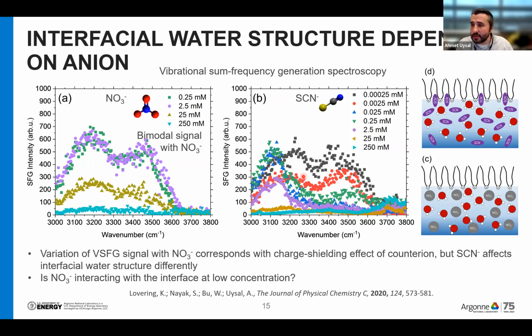And one more note about this data, I really love this data, because when you look at this, we are increasing the bulk concentration of nitrate 10 times from 0.25 to 2.5 here, and the SFG signal is not changing. Now, if we use only SFG, we can say, okay, there's not much nitrate adsorption at the interface. But when we do X-ray reflectivity from this interface, we see that actually nitrate is coming to the surface, but it is not affecting the SFG signal significantly, possibly because the oxygens of the nitrate help them incorporate themselves into the hydrogen bonding network without disrupting it that much. So this is a very interesting observation.